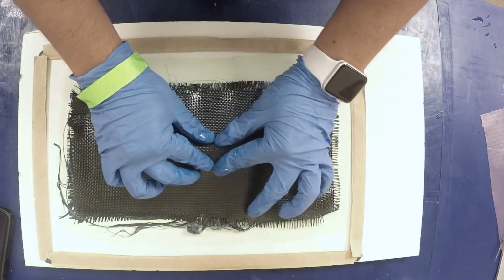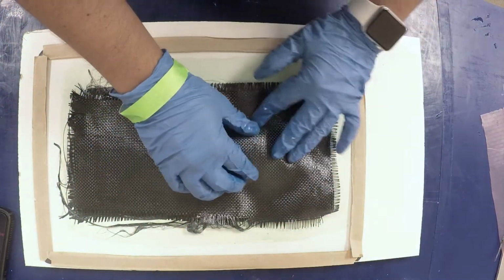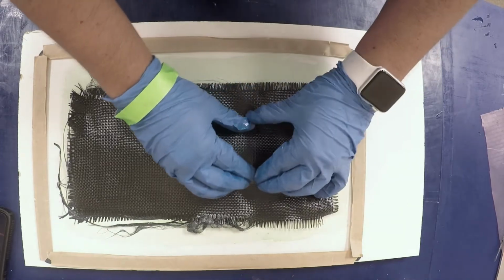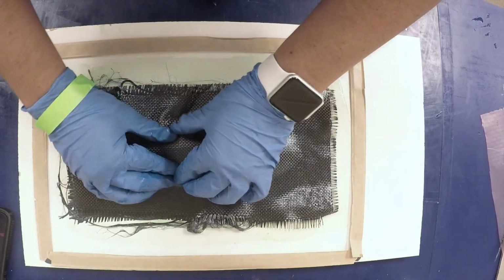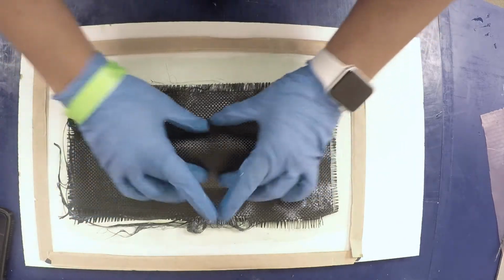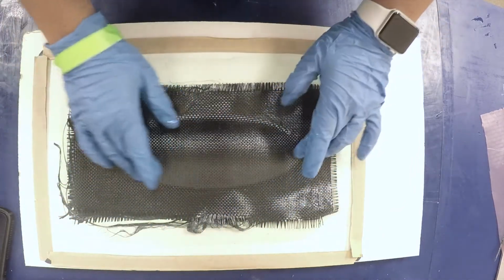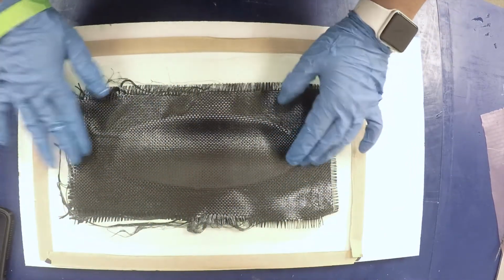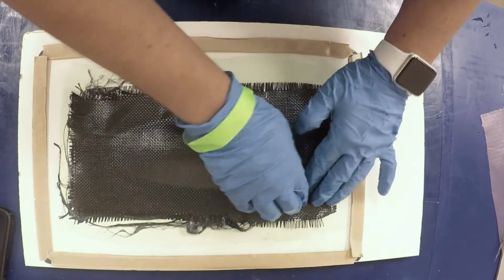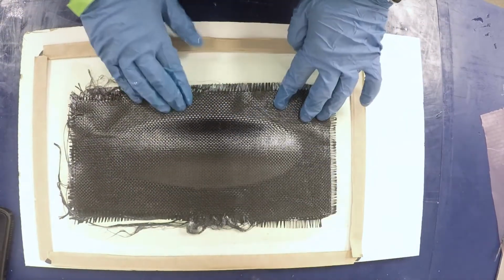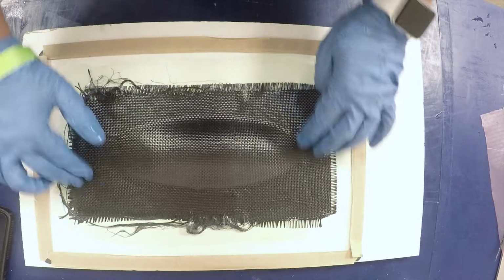Keep in mind that for more complex geometries, the laminate may not be capable of conforming to the shape without the use of relief cuts. If it does become necessary to cut the fibers, be sure to allow for different layers to overlap over the cut, and to cut relief cuts at different locations to allow the fibers to remain uncut at any given section of the laminate.